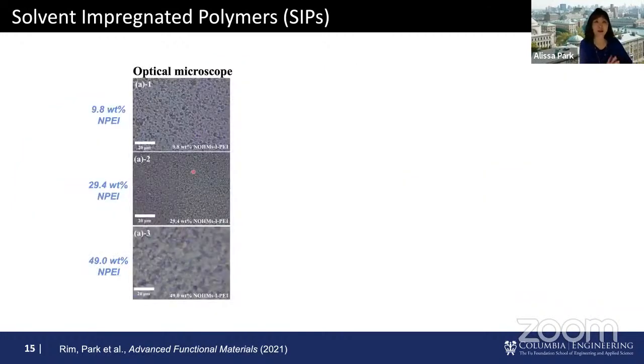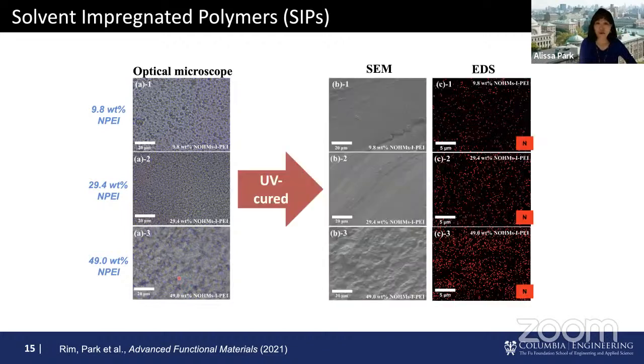So here are optical microscope images after making them emulsified. From about 10 weight% all the way to 50 weight% loading of NOMs. And as you can see from the lowest loading, you see small droplets, but by the time 50% is almost like a well-mixed system. After UV curing, if you look using naked eye, you can see them as if it looks like just a polymer film.